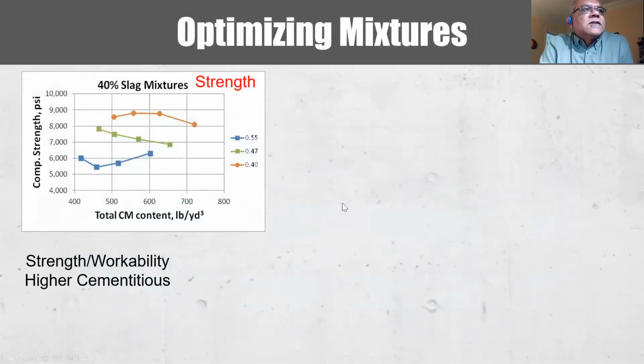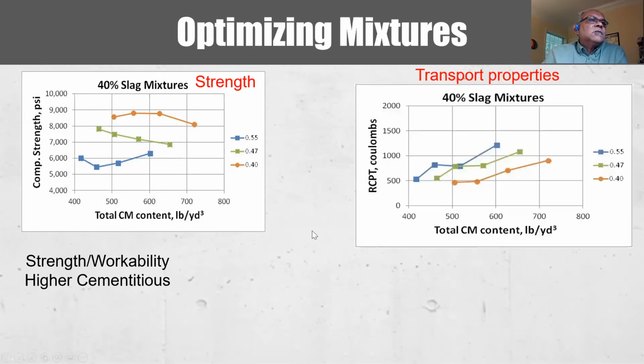What we also see is that if you only limit yourself to strength in a specification, you will get strength, because this will be padded so that you get very low probability of low strength results, and to avoid any problems associated with testing concrete also. In general, as you increase the cement content at the same water cement ratio, you don't see a great difference in the strength provision. So strength and workability generally drive a higher cementitious content in concrete mixtures.